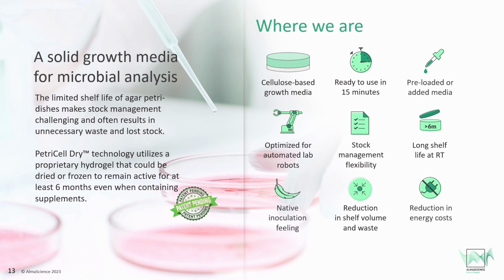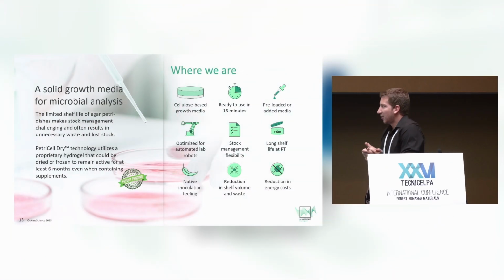Because it has a long shelf life, the way we tested, we have samples now reaching 9 months. So we say here 6, but it's already reached samples reaching 9 months. It has a long life, and this shelf life is at room temperature, which lowers a lot the requirements regarding temperature for stock and also the energy consumption.